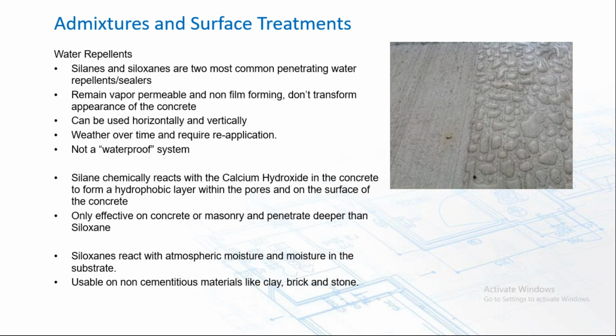Silanes chemically react with calcium hydroxide in the concrete to form a hydrophobic layer within the pores and on the surface of the concrete. Really only effective on concrete or masonry, and penetrates much deeper than the siloxane. It does require that calcium hydroxide to react with. Siloxanes, on the other hand, react with atmospheric moisture and the moisture within the substrate, and then you can use those on non-cementitious materials like clay, brick, and stone.